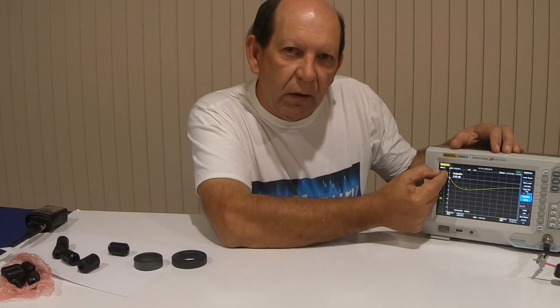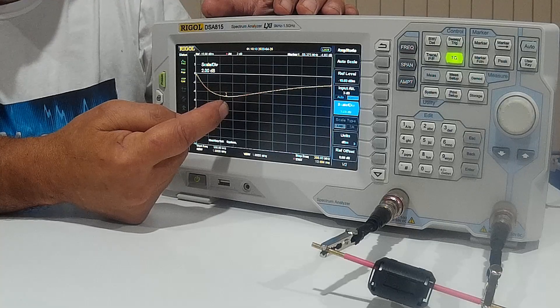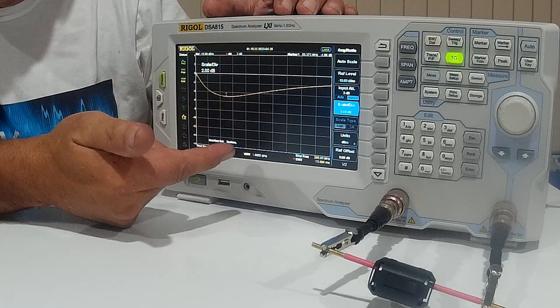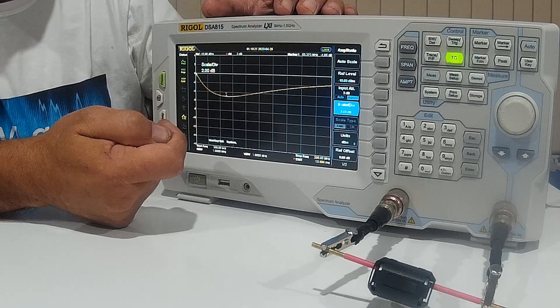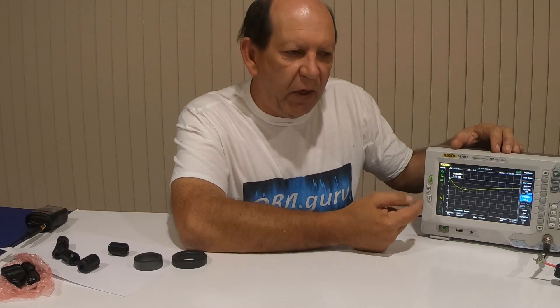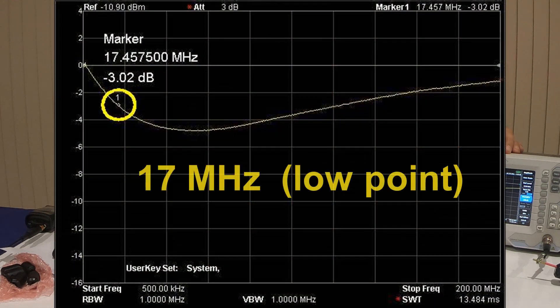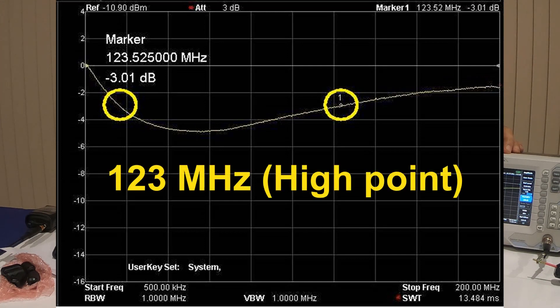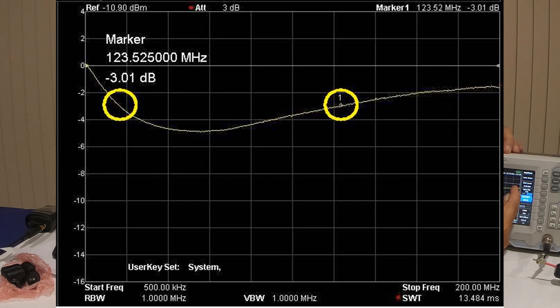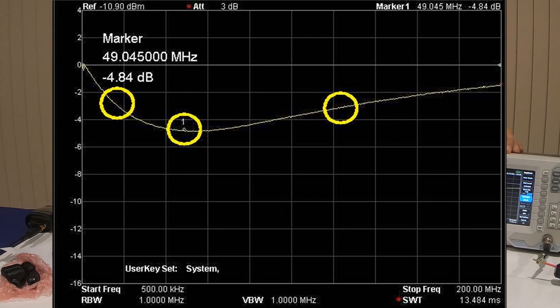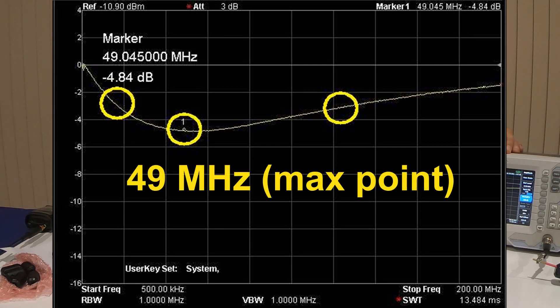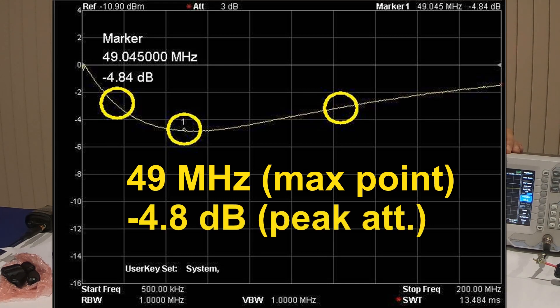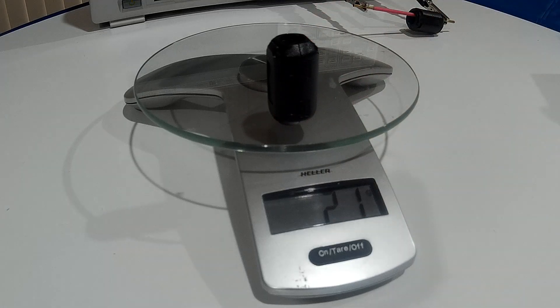With this testing arrangement I'm able to plot the frequency and performance of any ferrite device and compare between ferrites, and see what happens when I use them in different combinations. The trace for this ferrite shows a curve heading downwards, and that shows the amount of attenuation or absorption the ferrite has at any given frequency — the further down, the greater the absorption, measured in dB. I'm interested in five pieces of information for every ferrite device I test: the minus 3 dB point, the top 3 dB point, which together give the bandwidth; the frequency of maximum attenuation; the amount of attenuation at that frequency; and the weight, because the mass of the ferrite item is another variable.